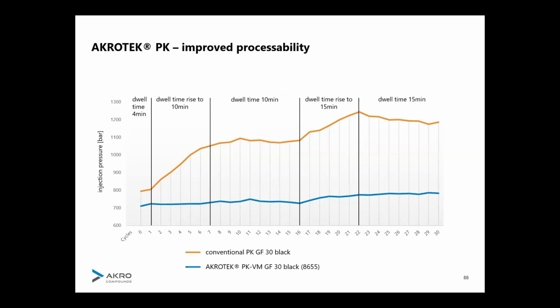behavior in the mold. In the beginning, they were on a similar level, and then we started to increase the dwell time just to make the material suffer a little bit more under temperature and to activate the cross-linking process. And we could see that by increasing the residence time in the injection molding barrel, this standard polyketone really goes up a bit, and you can even do it further. So we had a stable condition here, and then we increased it by another 5 minutes, and it went even higher. So it was quite logical.